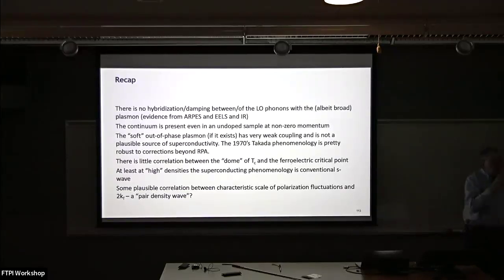And indeed, the quantum oscillations are very good. It's a very good metal. And as you saw, the mean free path is extremely long. So there's very little evidence for that, except for that one set of experiments from Jeremy Levy's group. But of course, that's a very different system. There is also very strong evidence that we are in the BCS regime. The pair size is much larger than the interparticle spacing, so all of this really looks like BCS. Okay, good.